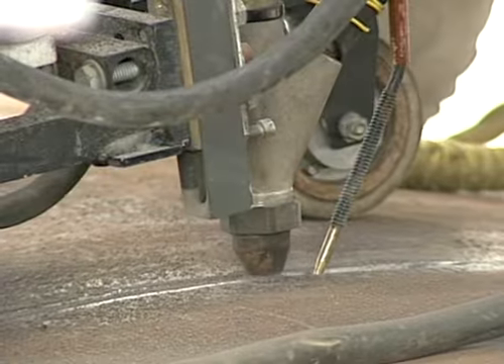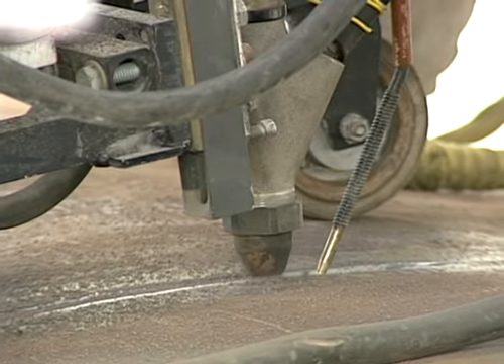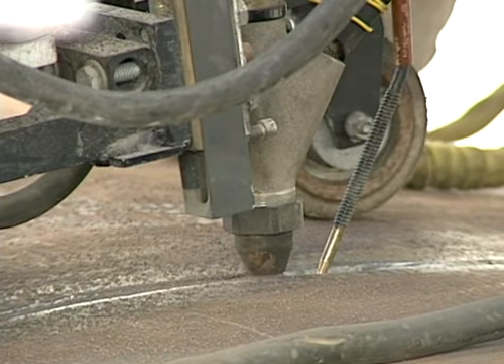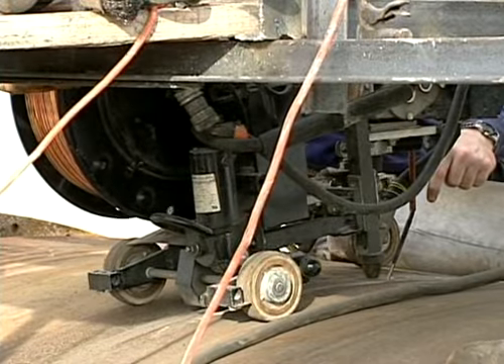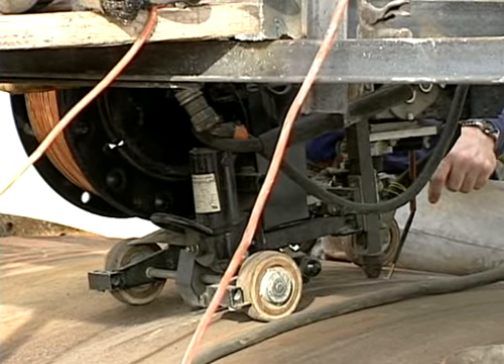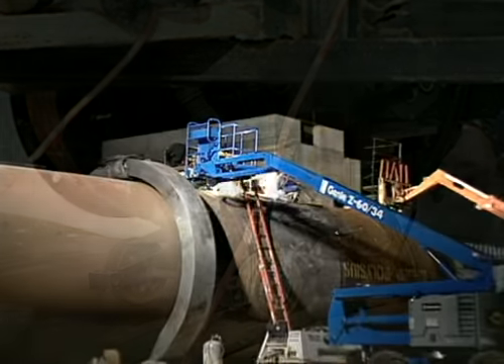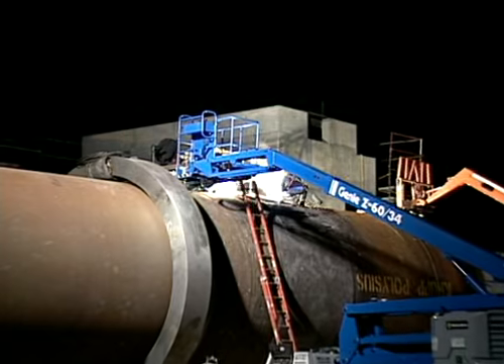Welding is planned in sequences that preserve alignment. Rapid and heavy deposit of weld metal can distort the axial linearity of the shell. These forces must be balanced by depositing weld in alternating locations 180 degrees apart. The submerged arc welding process is used to complete the exterior portion of the seams. This necessitates turning the shell at the precise speed to match the speed of welding. The welding continues day and night.